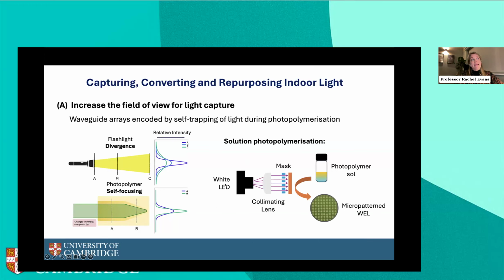So in the lab, this is how we make these things quite simply. We take a white LED light and we shine it through a few lenses and then pass it through a mask, and that's going to give us our pattern that we're going to encode into our polymer film. And then it shines onto our precursor solution. And so when the light hits this precursor solution, shown in orange, this triggers this chemical reaction, this photopolymerization, and the material transforms from a liquid to a solid material.